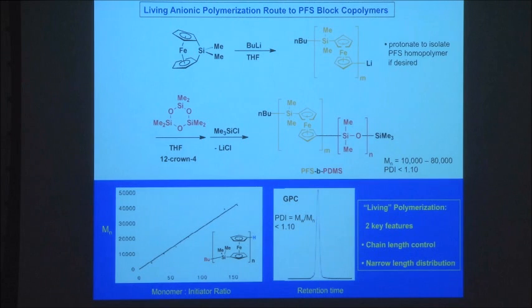And the reason for this is, in a living polymerization, every initiator molecule generates one polymer chain. So the ratio of the initiator to the monomer will control the chain length here. So if this is 1 to 10, the value here will be 10. If it's 1 to 100, it should be 100. So as you vary this ratio, you can control the chain length. So this is one key feature of living polymerization. The other key feature is that the initiation step is fast.